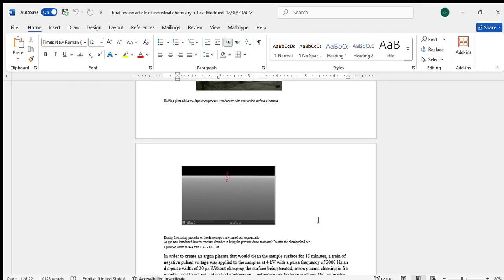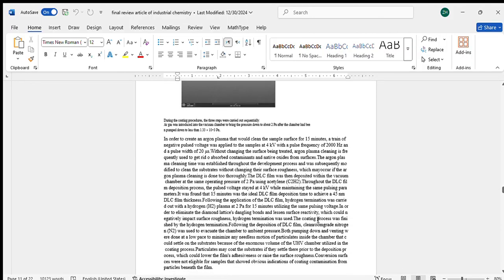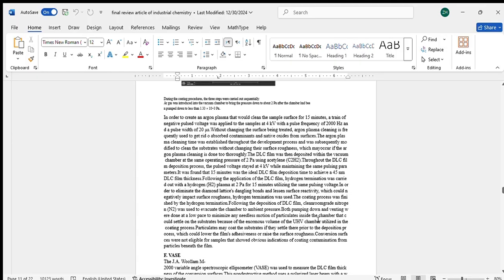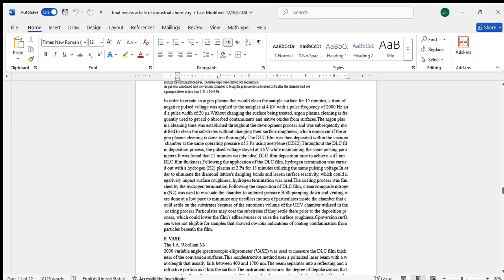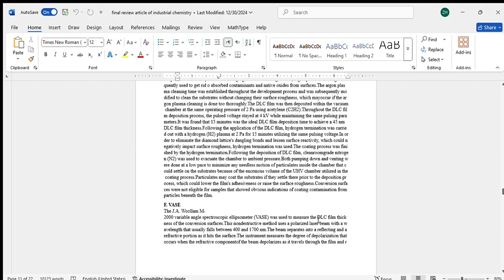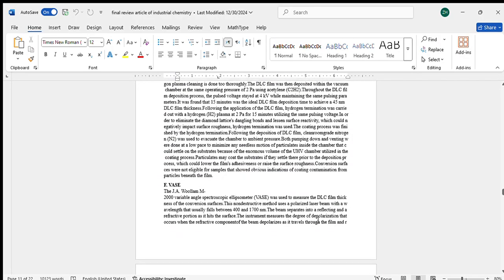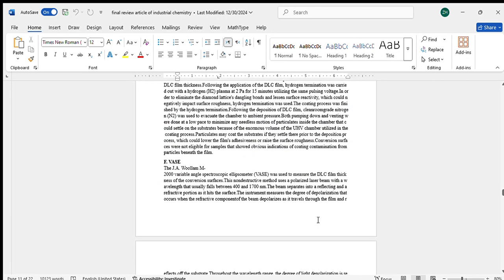That thickness is about 45 nanometers, and the surface roughness is low, less than 5 angstrom. So this is all about the DLC coating, meaning diamond-like carbon coatings. If we look at section F, it was VASE, meaning variable angle spectroscopic ellipsometry.